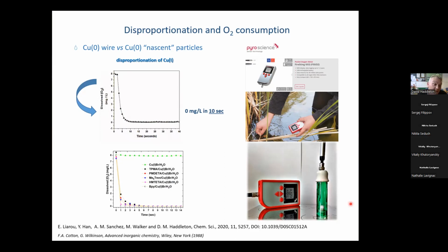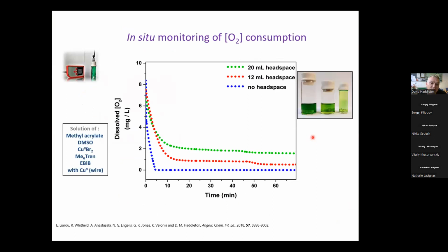So we need to do this in radical polymerization as well now. And it turns out, here I've got 3 different reactions, which are methyl acrylate, doing polymethyl acrylate in DMSO solvent. We've got Me6TREN, which is our ligand, and we're using copper wire. So essentially, you probably see here, we've got some copper wire wrapped around the magnetic stirrer. And you'll also see that this one's dark green, this one's a bit lighter, and this one's much paler.